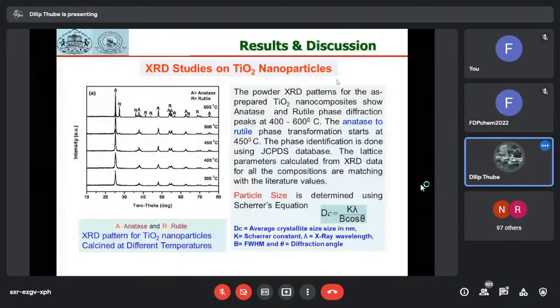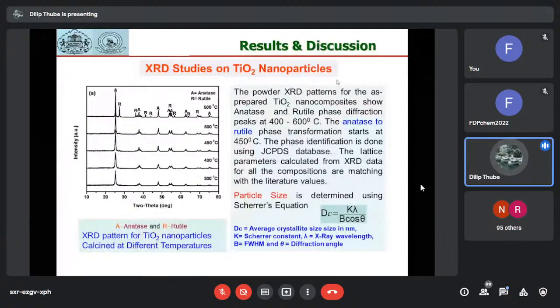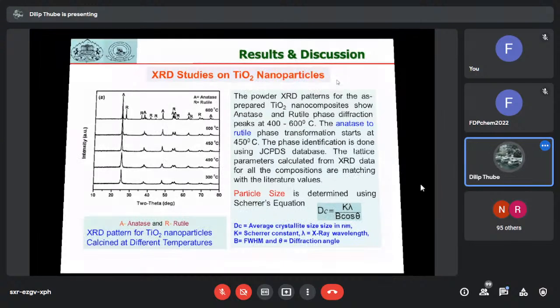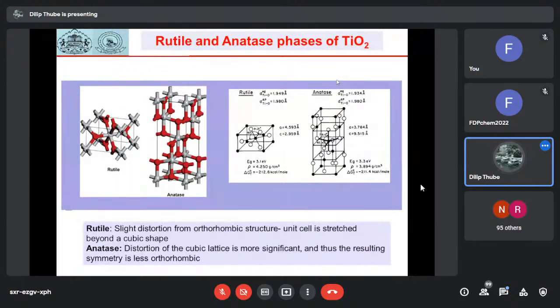This slide shows the XRD pattern, and at about 600 degrees Celsius, the rutile phase is evident, and therefore we have to think about the sintering temperature. Anatase phase is suitable for photocatalysis, whereas rutile phase is not suitable, and therefore we want a material only with the anatase phase, so we have to think about the temperature at which only anatase phase will be there and not a rutile phase. So with this, we have finalized a sintering temperature.